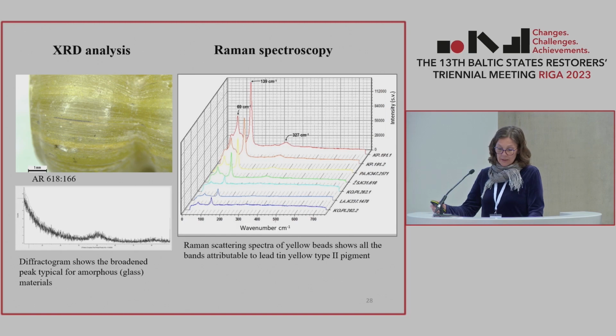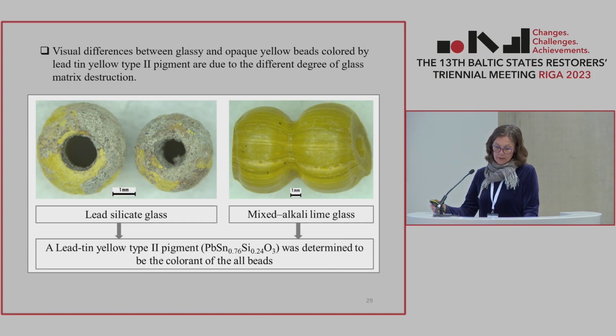Unfortunately, determining the lead tin yellow pigment by the XRD method was unsuccessful because the matrix of the beads is amorphous material and the concentration of the pigments is relatively small, although its grains are very clearly distinguished. However, a summary of Raman scattering spectra of yellow beads shows all the bands attributable to lead tin yellow type 2 pigment. The general conclusion is that visual differences between glassy and opaque yellow beads colored by lead tin yellow type 2 pigment are due to the different degree of glass matrix destruction.